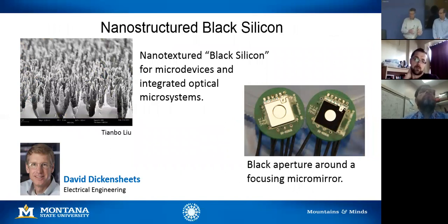Shifting gears from SU-8, now I just want to talk about another etch process that we have developed for the inductively coupled plasma etcher. The point I'd like to make here that's important is this nano-textured surface of silicon. This used to be a shiny surface of silicon, but with the right process parameters, we can make an unmasked film. There was no lithography done here. We just put bare silicon in the etcher, ran the etch, and we get this very rough surface.